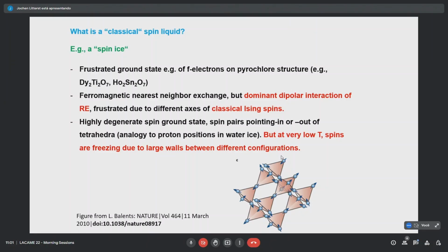The interaction there is, in principle, from nearest neighbor to nearest neighbor, that's ferromagnetic. But the dominant interaction you have to face here, since you have very large spins and large moments, is a dipolar interaction, which is long range. However, this interaction will be frustrated since locally there are easy axes for these Ising spins, and they are looking inside or outside of these tetrahedra. And for sure, there are many possibilities to arrange that, so you will end up in a highly degenerate spin ground state, with spin pairs pointing in or out of these tetrahedra.